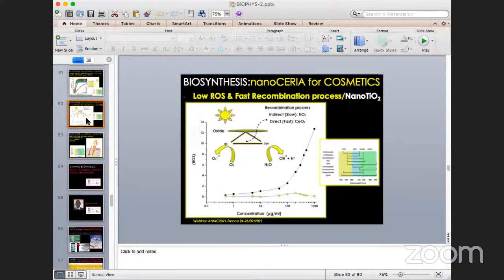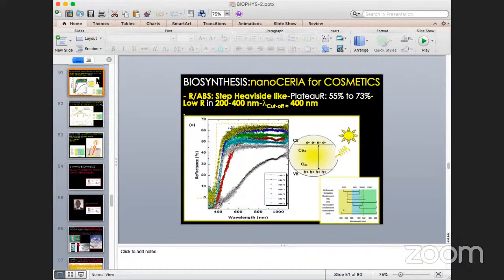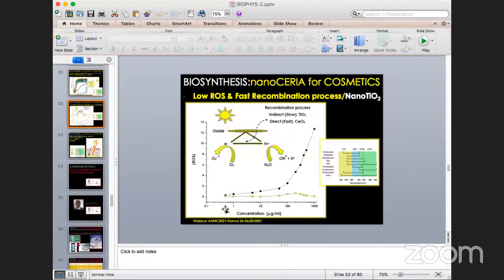Because as I mentioned, for example, the case of this cerium oxide, it will definitely be absorbed by the cosmetic industry, because the cerium oxide biosynthesized, at least by this natural extract, has a fantastic cutoff, a fantastic optical selectivity. In addition, relative to the normal zinc oxide and TiO2, which are used in cosmetics and which have quite a high ROS production, this cerium oxide has zero. So it's not toxic at all, even at a high concentration. So you would understand that when we publish this paper, the industry will jump on it and will try to make such a kind of cerium oxide.